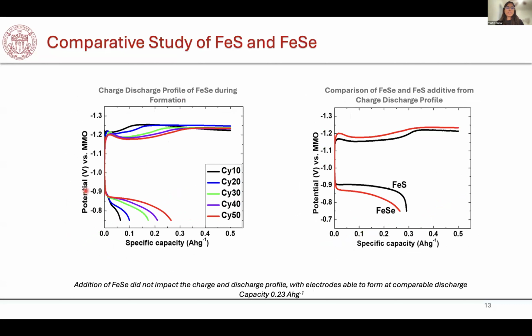So the polarization curve, basically you plot the potential with respect to the specific capacity, and it tells you exactly how the charge and discharge profiles look for each respective cycle. During the formation for iron selenide, with each cycle, this voltage plateau keeps on increasing and becomes stable by the 40th and 50th cycle, which indicates the end of the formation. So coming to the comparison of both the additives after the end of formation, in terms of their polarization curves,